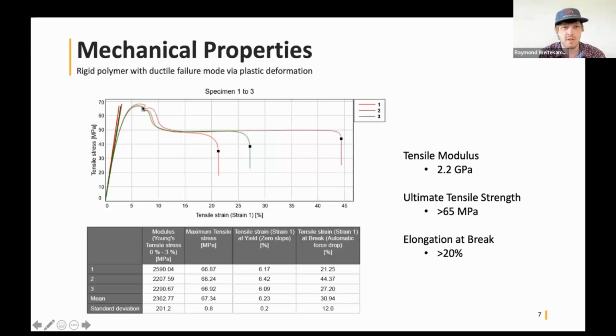There's a little notch there that's an artifact from the way we do the test with an extensometer, so you can ignore that. But then the UTS is about 65, 70 megapascals, and then it'll yield and turn over. And we've set the spec for COR Alpha to be at least 20% elongation at break. Sometimes we get higher than that.